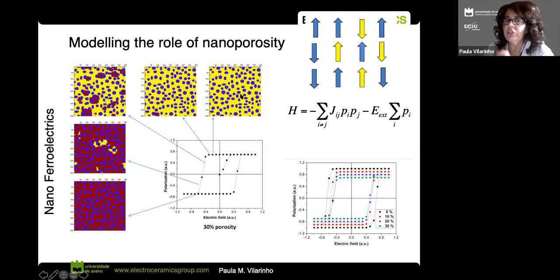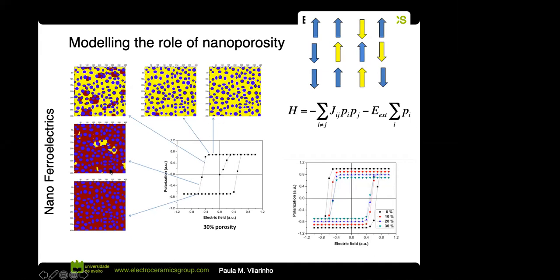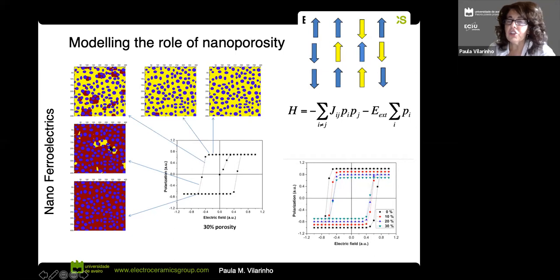So we were increasing the amount of porosity, and we were also increasing the localization and the shape of the porosity, and then trying to switch. So this is polarization, this is electric field, and as I mentioned before, this is a hysteretic curve. You can have this for ferroelectrics and for ferromagnetics. What was interesting is that, depending on the porosity, the switching was being facilitated. And that's quite interesting. We were not expecting that. We were expecting porosity to make things difficult, including switching. And that's not what is happening.